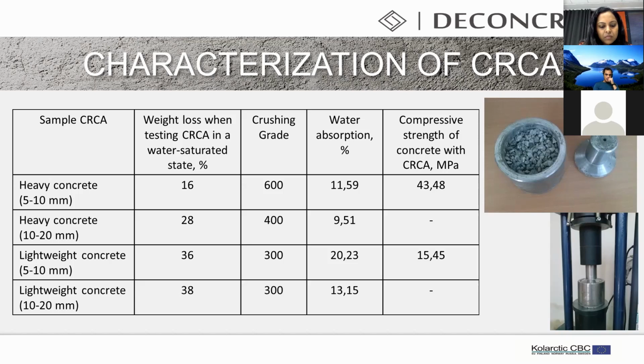And we made concrete samples in the form of cubes with crushed stone of 5 millimeters from light and heavy concrete, and used that as an aggregate with the same cement content and equal water cement and water solid ratio. After 28 days of holding under normal curing condition, we tested the compressive strength. The test results show the compressive strength of concrete with crushed stone from waste light and heavy concrete was 15 MPa and 43 MPa respectively.